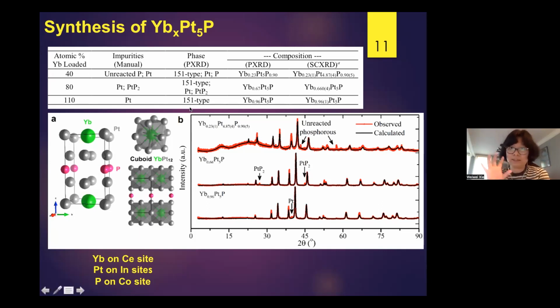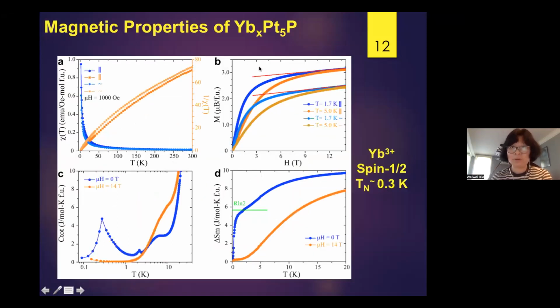And then we did different ratios. So we found out that in this system we can load from 0.25 ytterbium until like 100% ytterbium into the system. So see here, we go from 25% until almost 100%. And then the magnetic property and the superconductivity property are completely different. So what we found is, if it's fully 115, so ytterbium 1, platinum 5, and then phosphorus 1,